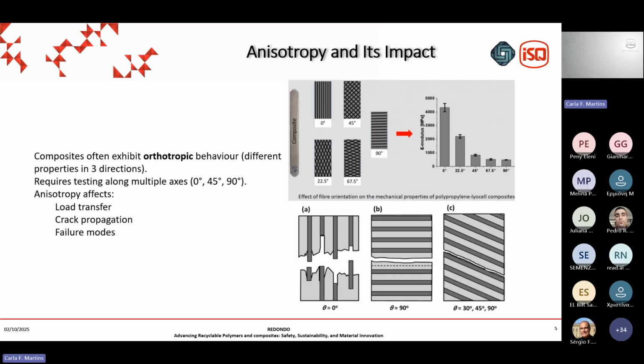This anisotropy or orthotropic behavior in different directions means that to characterize a composite, we need to test in different directions, typically at 0 degrees, 90 degrees to the fibers, and eventually 45 degrees in order to get a better characterization of their mechanical properties.